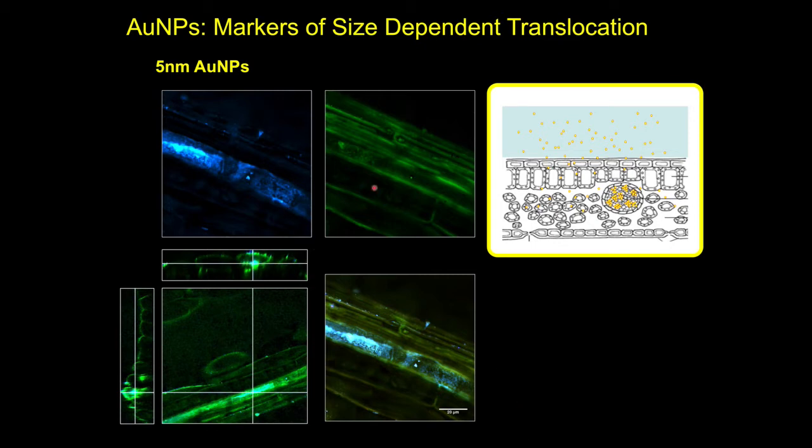In the green signal, you can see the chemically specific stimulated Raman gain signal that comes from the cellulose in the plant cell walls in the root. And in the blue, we have the excited state absorption that comes from aggregated 5 nanometer particles that have aggregated within the roots. The key issue here is that 5 nanometer particles on their own, isolated particles, do not